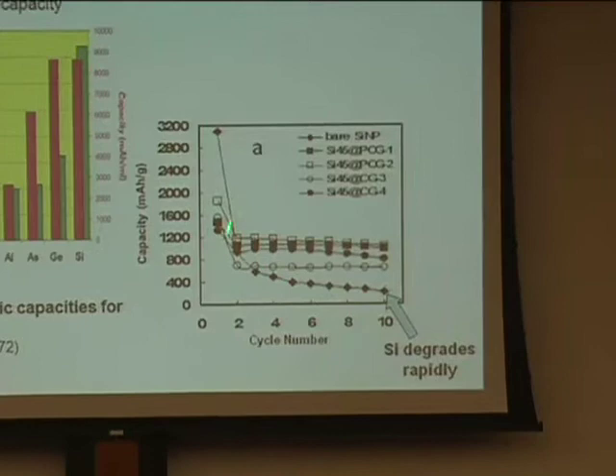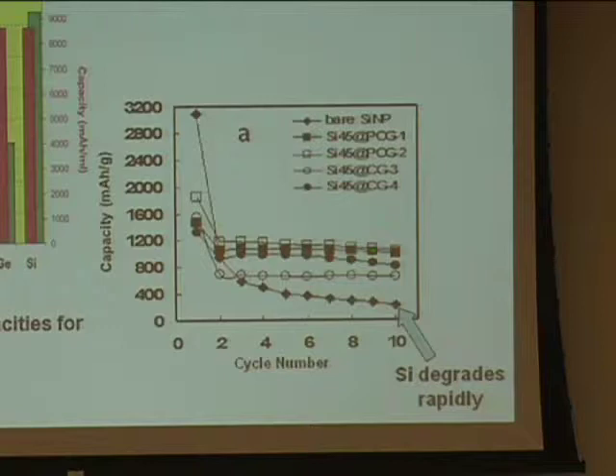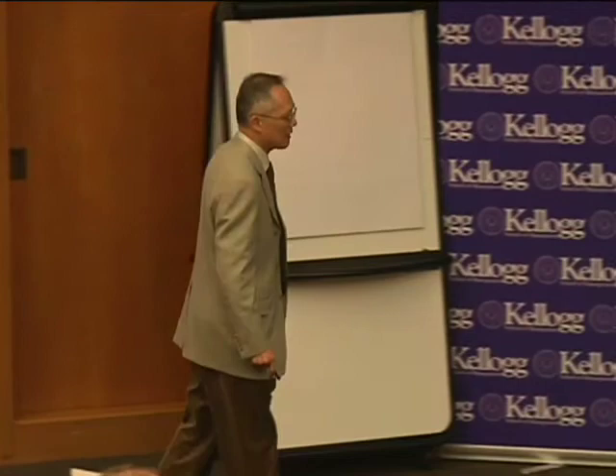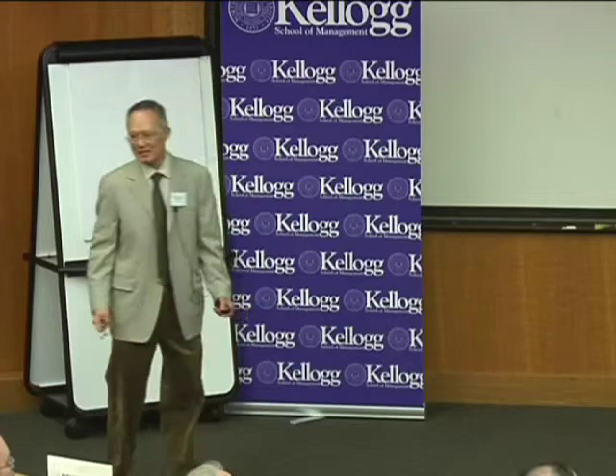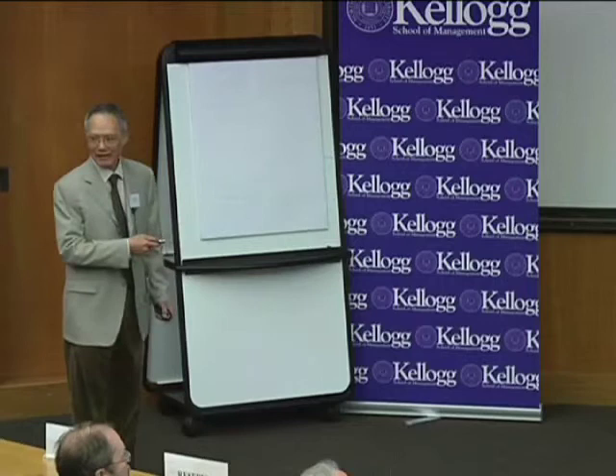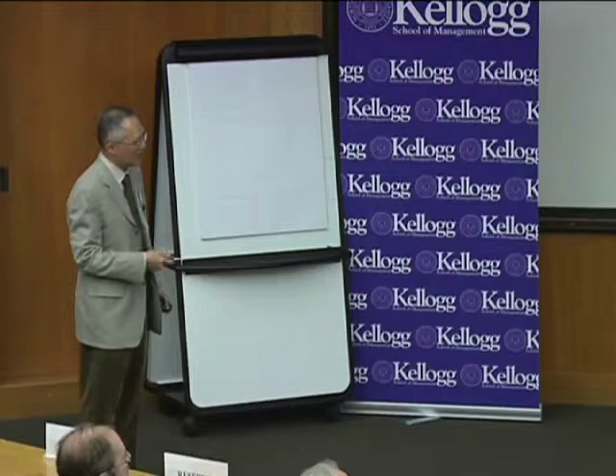Well, what one would like to do is to stabilize this, rather than having it die, to be able to maintain the capacity for many cycles of charging and discharging. For the type of application we're envisioning, automobile applications, we need to maintain this charge-discharge capacity for at least 1,000 cycles, right? Not 10 or 20. Well, what we have been looking at along this direction is how to stabilize this drop in the capacity.